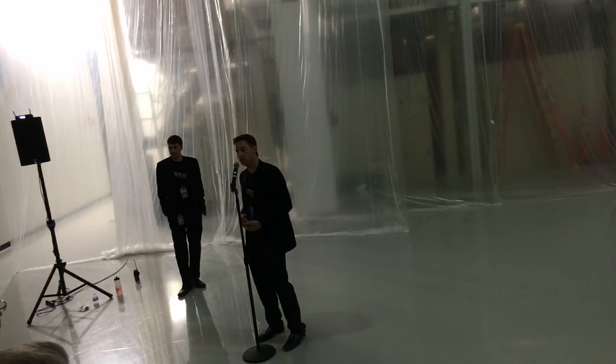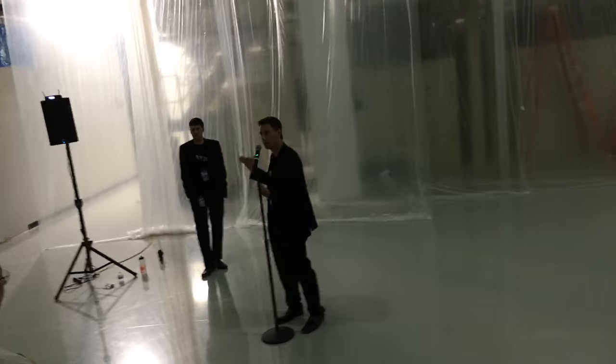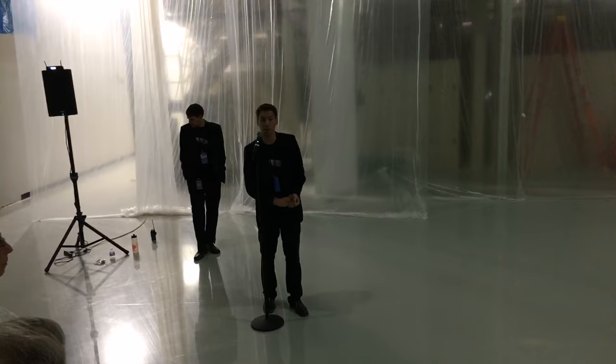We then take that foil, turn it vertical, and go up to the top, where we have our second coating booth. And then what was the bottom of that foil is now the top. And we apply another layer of active slurry to the top. And then it dries in a similar fashion, going back down in that direction. So by the time we get to the far end, we have dry active material on both sides of this